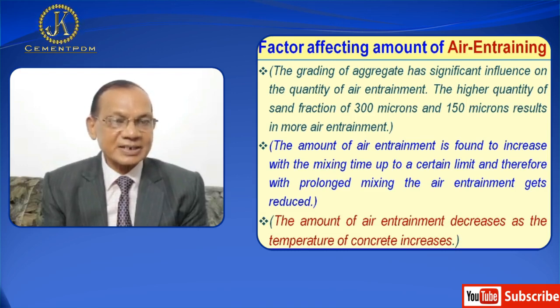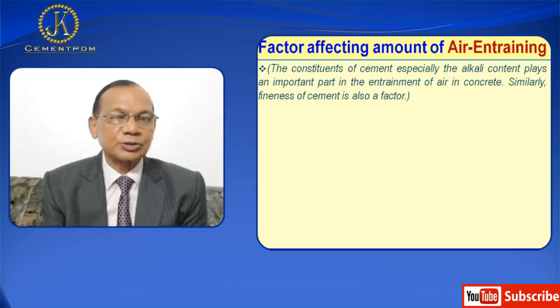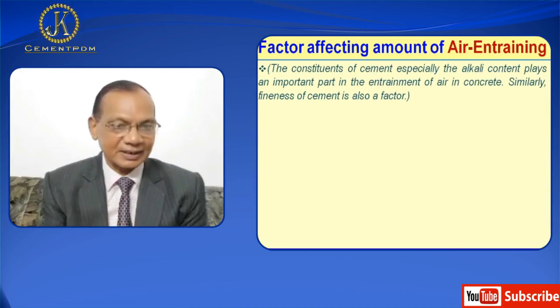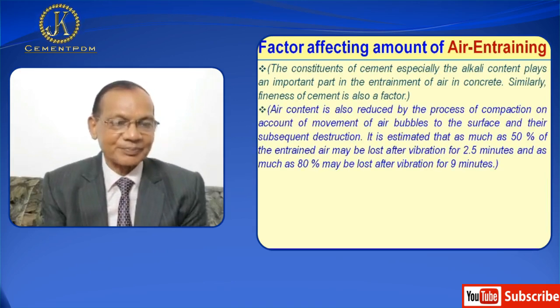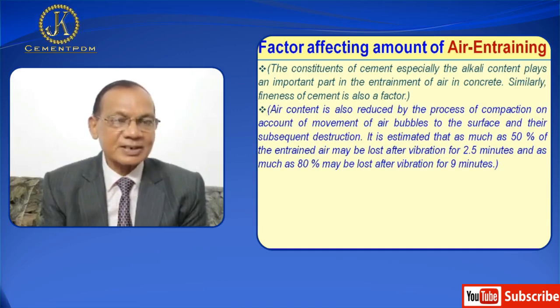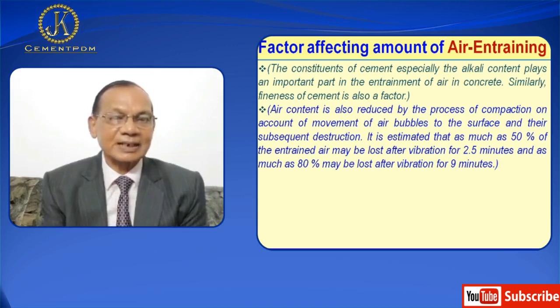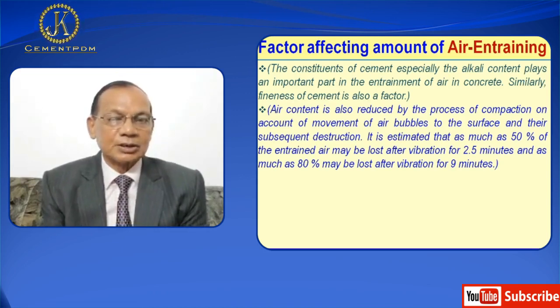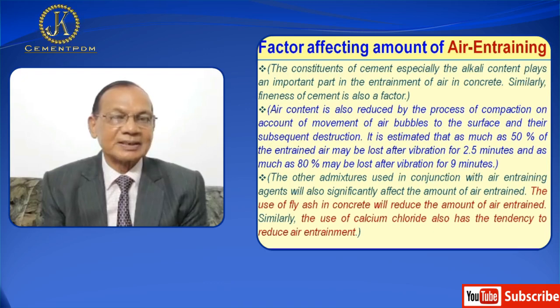The amount of air entrainment decreases as the temperature of concrete increases. The constituents of cement, especially the alkali content, play an important part in the entrainment of air in concrete. Similarly, fineness of cement also affects air content. Air content is also reduced by the process of compaction due to movement of air bubbles to the surface and their subsequent destruction. It is estimated that as much as 50% of the entrained air may be lost after vibration for two and a half minutes, and as much as 80% may be lost after vibration for nine minutes.